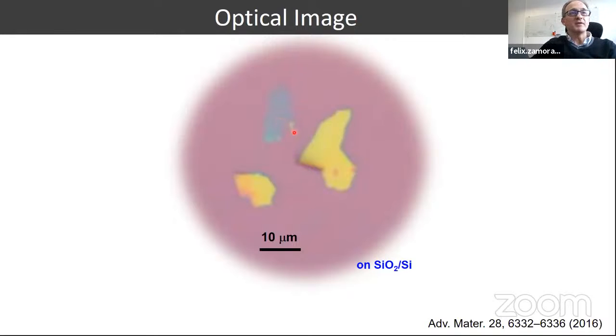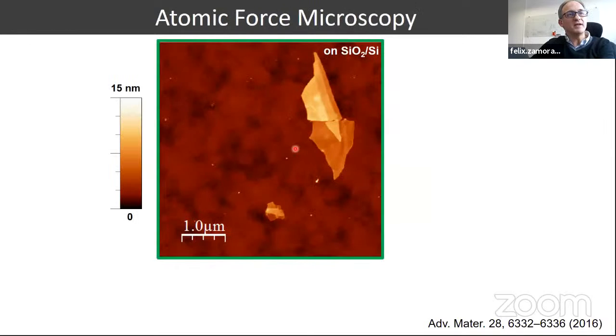Those in yellow represent a big thickness in comparison with those in blue, which are slightly smaller in thickness. But when we tried to characterize this blue layer, we realized that around it, let's say over here, if we use AFM, atomic force microscopy, we can find something that we couldn't see under the optical microscope: smaller layers that we cannot see by optical microscope.